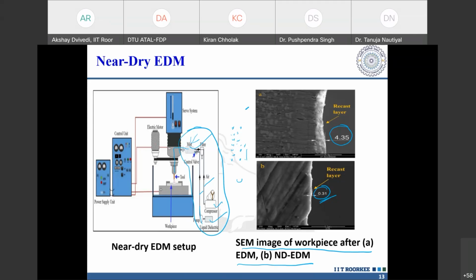Of course, you should have a design for that. 20 lakh rupees system, which was the capital cost of an EDM. If you have to convert it into a near dry system, you just need to add another 20,000 to it. The material removal rate is increased by something around 5 times. Surface quality is improved by something around 2 times. You have bare minimal recast layer. The process is environment friendly. It is non-toxic. Will you go for this process?